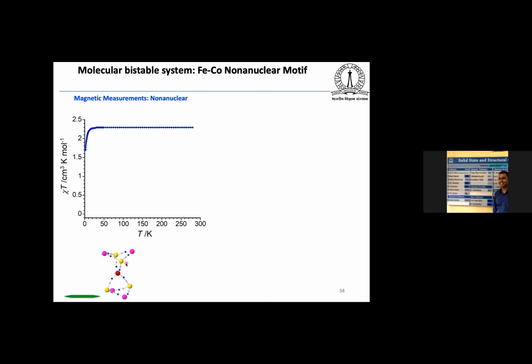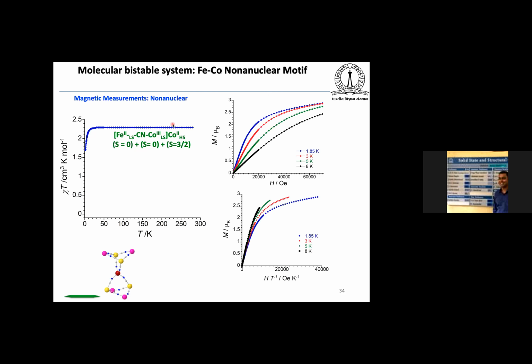We have not observed any metal to metal electron transfer in this nonanuclear unit or in the one below it. We have only observed the χT value coming from this cobalt 2 tetrahedral high spin system. So here you can see that the system is composed of iron 2 low spin and cobalt 3 low spin, which is diamagnetic, and you have only cobalt 2 high spin, and this is the signature of cobalt 2 high spin, and this also matches well. The ground state is mainly due to the cobalt 2 high spin present in these systems.